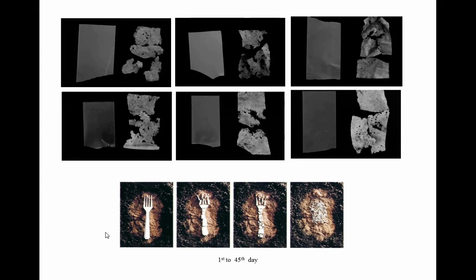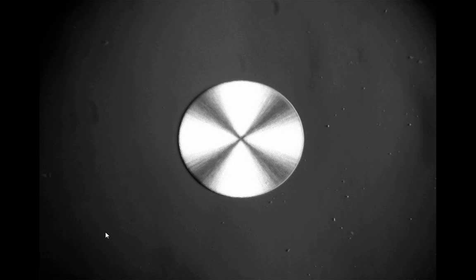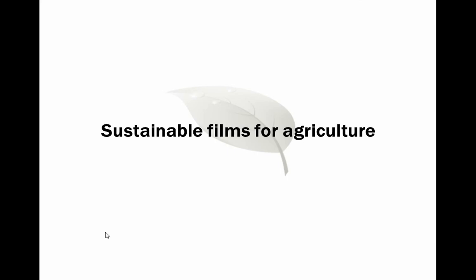The other beauty about these materials is they are naturally water resistant — they don't dissolve at all — so they have great material properties for most of the applications we're looking at. We're working hard using cheap waste resources and cheap processes to make them more cost effective compared to other commercial biodegradable materials. PHA is so pure it makes incredible large beautiful crystals when crystallising, which is both a strength and a weakness. We have to manipulate polymer properties to get malleable, ductile materials rather than brittle ones.